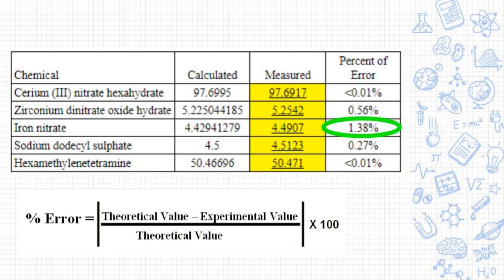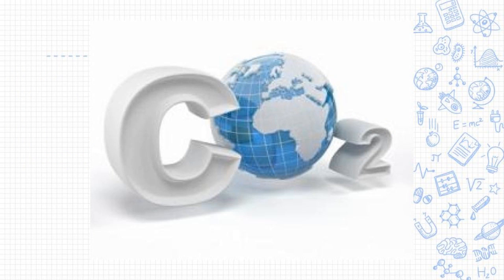But most importantly, all the chemical measurements were within 1% of the calculated value, except for the iron nitrate in the iron dope membrane, which was 1.38%. The chemical measurements and X-ray diffractions can be found on figures 30, 40, 42 in the written report. My hypothesis asked 2 questions to determine the best membranes. The first examined the amount of oxygen gained after the carbon dioxide oxidation compared to after the methane reduction. The second examined the amount of oxygen after recalcination compared to the initial state.